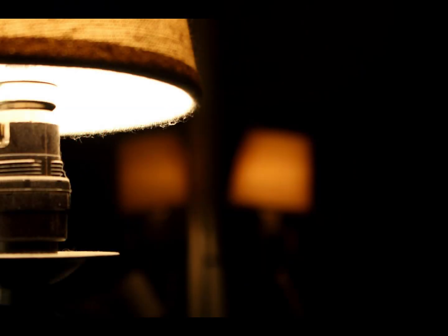Coiled coil filament. To improve the efficiency of the lamp, the filament usually consists of multiple coils of coiled fine wire, also known as a coiled coil. Light bulbs using coiled coil filaments are sometimes referred to as double coil bulbs. For a 60-watt 120-volt lamp, the uncoiled length of the tungsten filament is usually 580 millimeters, 22.8 in, and the filament diameter is 0.046 millimeters,